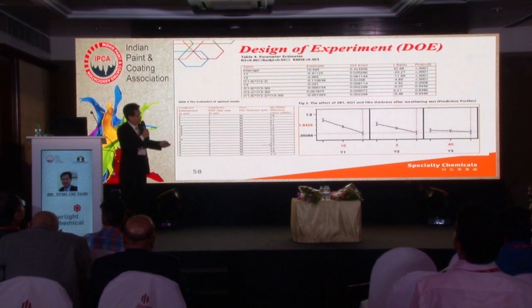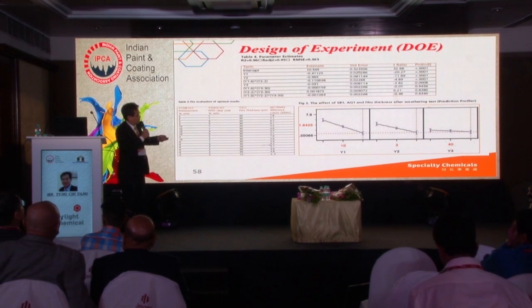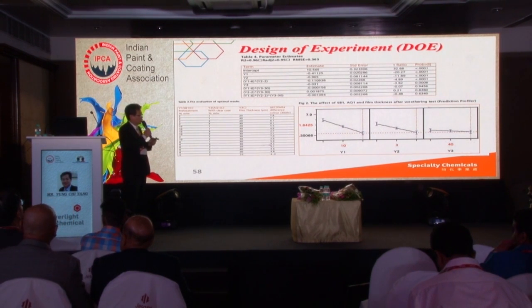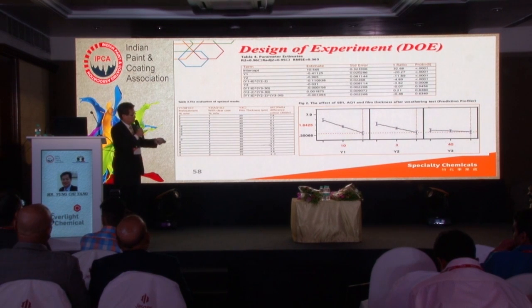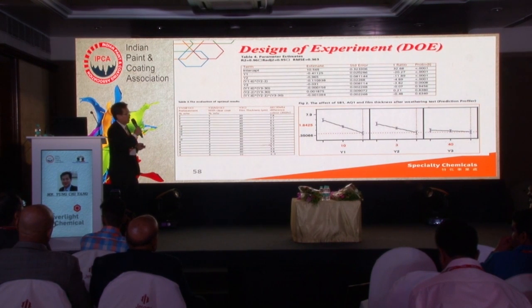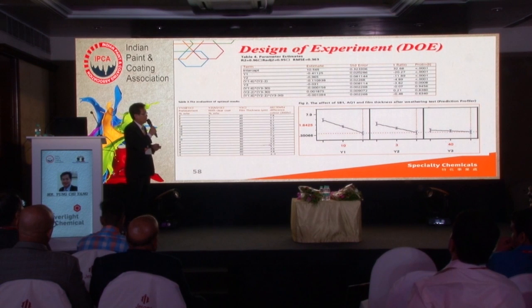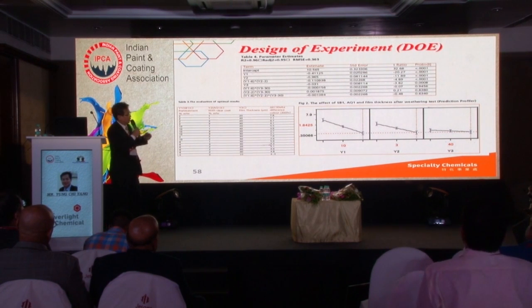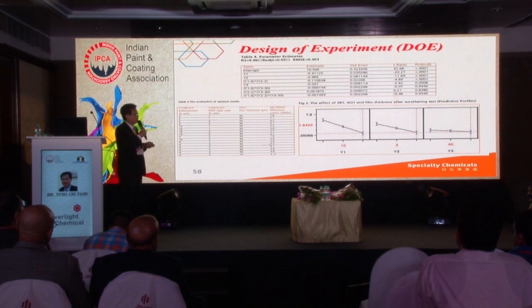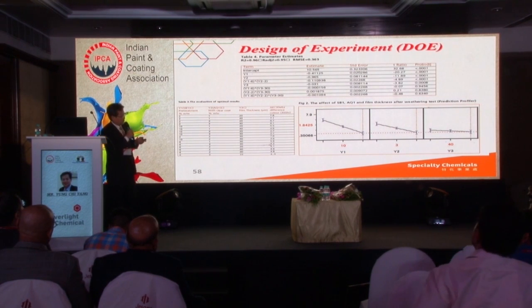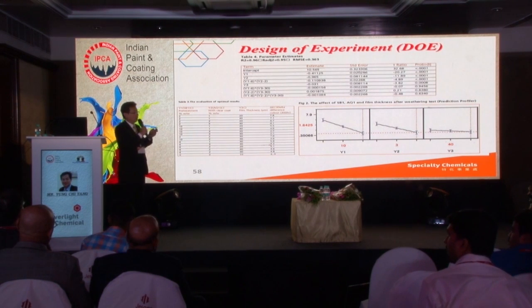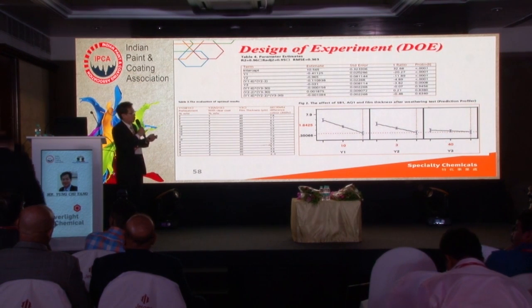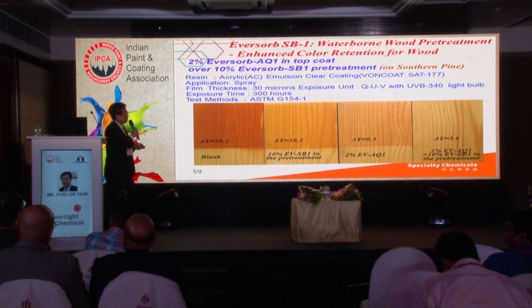And you can see the slope. You can see the wood pretreatment, Y1 is the wood pretreatment, Y2 is the AQ1 in the clear coat, Y3 is the film thickness. You can see the slope. If the slope is higher, you can get the best performance. So you can see the wood pretreatment and the AQ1 in the waterborne clear coat, you can get the best performance. And you can see at least in our test, after 300 hours, it can get the best performance.